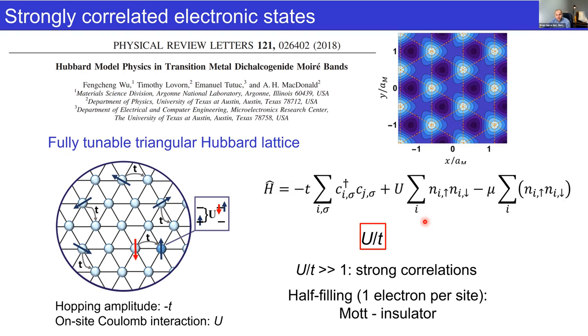And what's even more compelling is that in the TMD system, or in the 2D material system, we can really control T and U by the choice of twist angle and material to change the potential. As well, we can easily vary the chemical potential to change the fractional filling of these Moiré lattice sites.